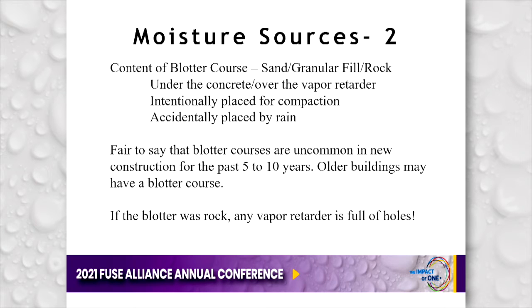I've actually been on sites where a vapor retarder was placed. We placed granular fill as a blotter course. It rained overnight. The next morning we're placing concrete, and we have to recognize that we now have a swimming pool liner full of wet granular fill that must dry through the concrete. It's going to take a long time. So it's fair to say that blotter courses are not common over the last 5 to 10 years, but older buildings may well have a blotter course. And if that blotter was rock, then I promise you that any vapor retarder that was placed is now full of holes because they dumped the rock on top of that plastic.